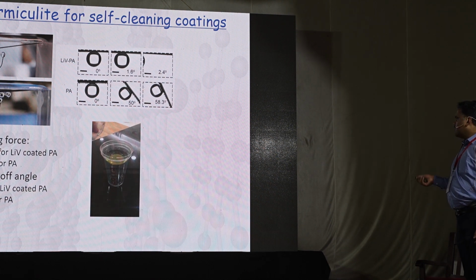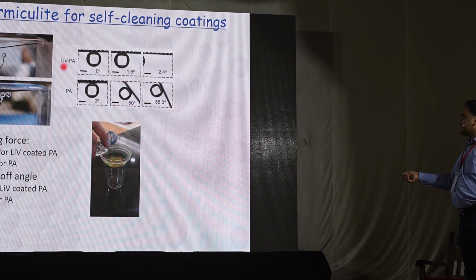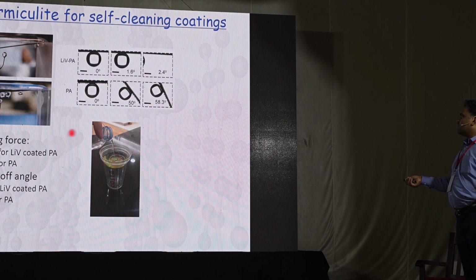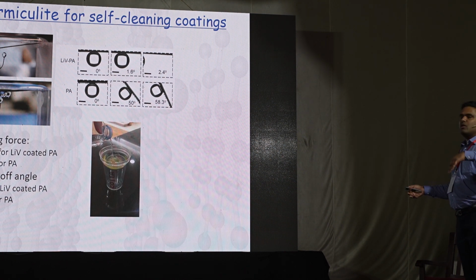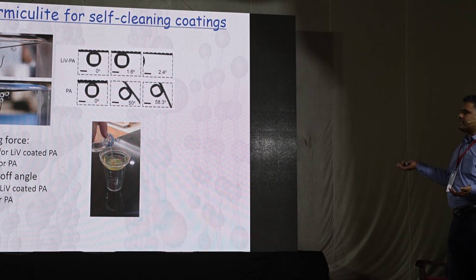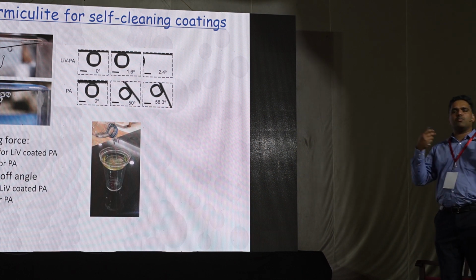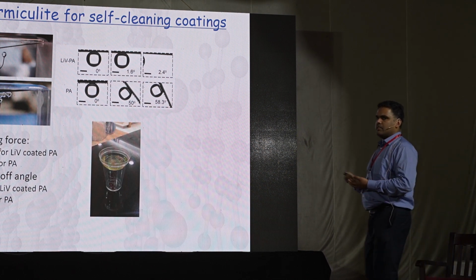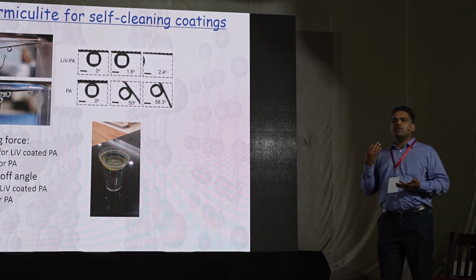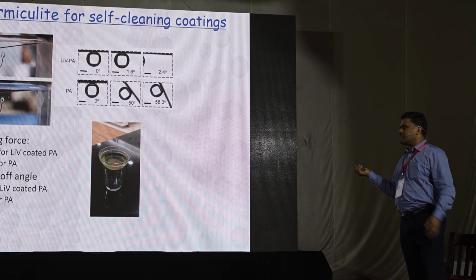So what you see here is that a layer of oil is there on the cup. When you put the water through this kind of membrane, water simply goes through. There is no resistance, but oil stays there. Oil cannot go through because it's a super hydrophilic surface. It's not size exclusion, it's a wetting property or surface tension phenomenon.